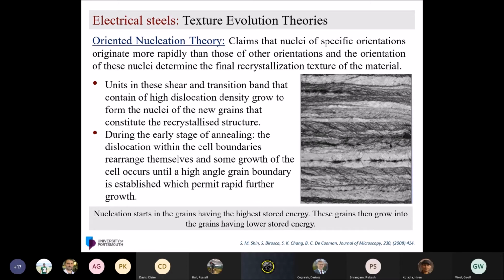These people believe that when you cold roll the material, there is a huge amount of shear transition and deformation bands, and the Goss or a specific orientation will originate and nucleate more rapidly than other orientations. And that will give a preference for the Goss to grow normally later on during the final recrystallization. So they think the Goss grain is actually nucleated during this recrystallization.